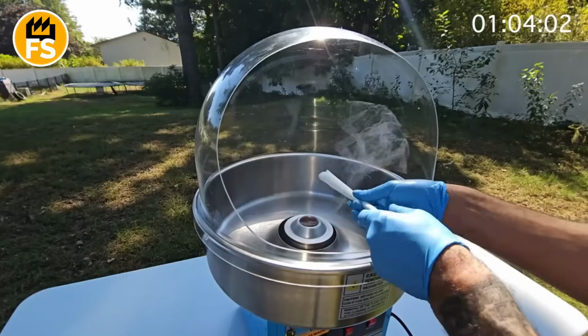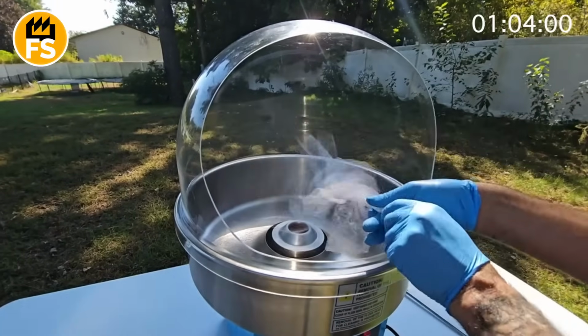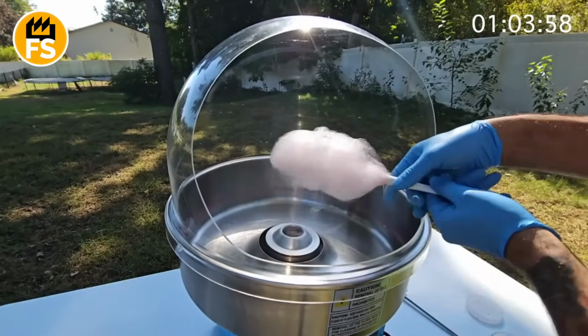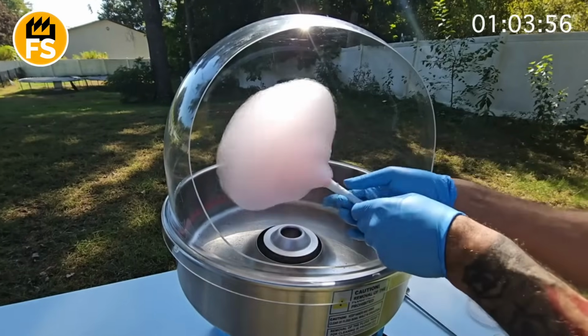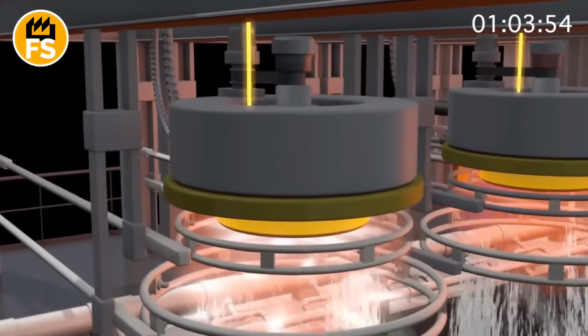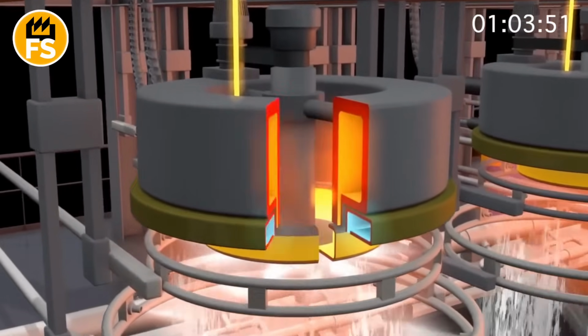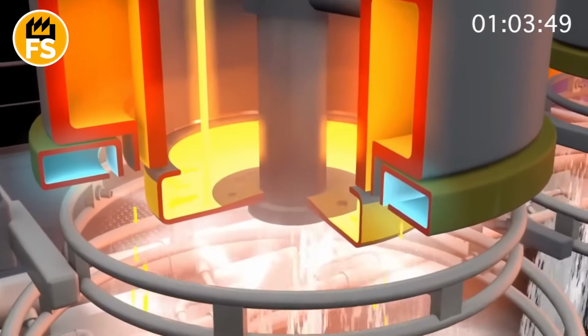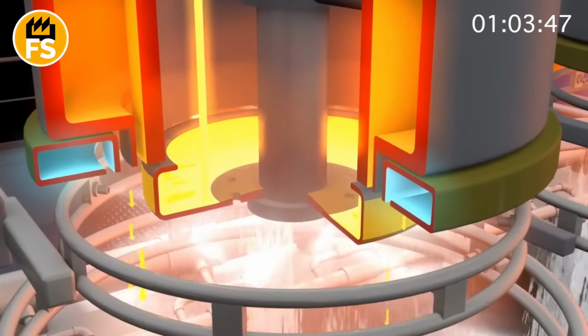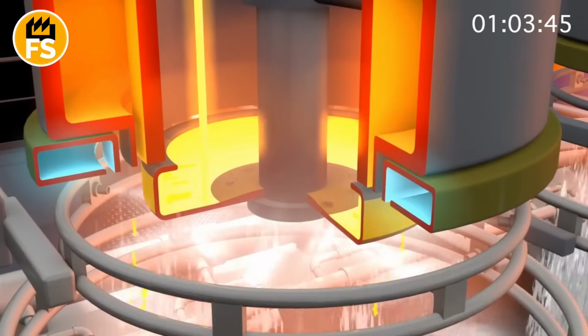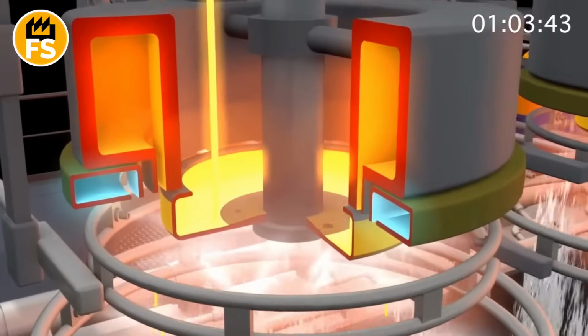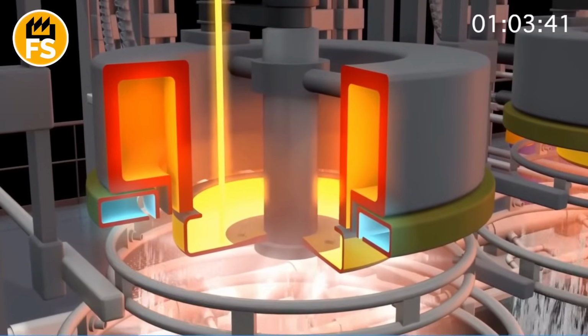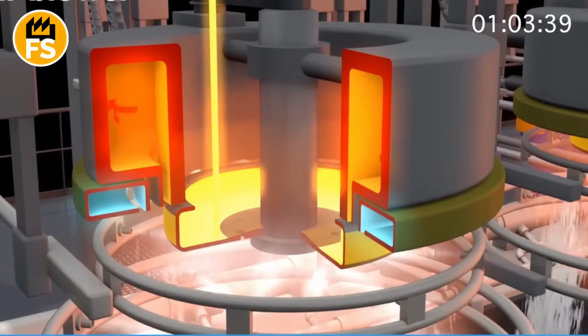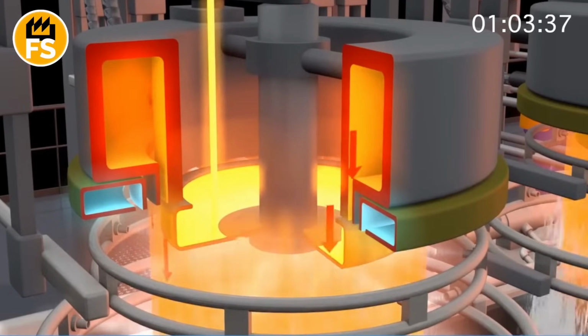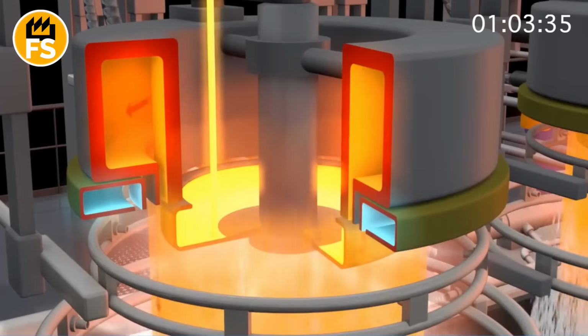You've seen a cotton candy machine, right? It has a rapidly spinning center where sugar is poured. Well, here it's almost the same, only instead of sugar, it's molten stone. A thin stream of this stone lava falls onto several discs that spin at a frantic speed, making thousands of revolutions per minute. When a drop of molten stone hits such a disc, centrifugal force instantly stretches it and throws it to the side in the form of an incredibly thin fiber, a few microns thick, thinner than a human hair.